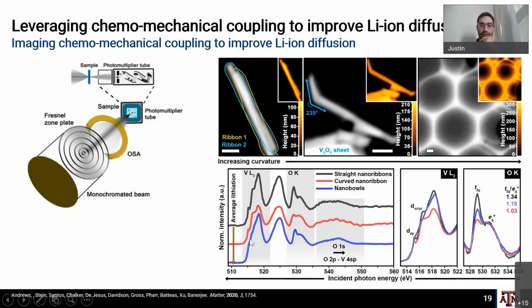Looking here, if you look at the DXY orbital, and I should have mentioned this in more detail earlier, what we notice as these things lithiate is that the DXY orbital, which is the split-off band at the bottom of the conduction band, is the first band to populate as electrons are donated to the structure. Spectroscopically, we see a diminution and darkening of that feature as the available states are populated by electrons.